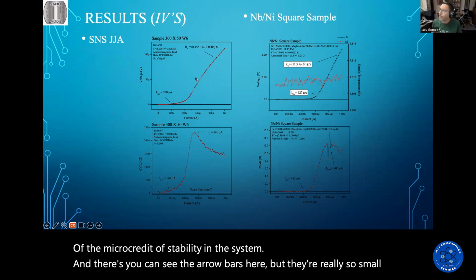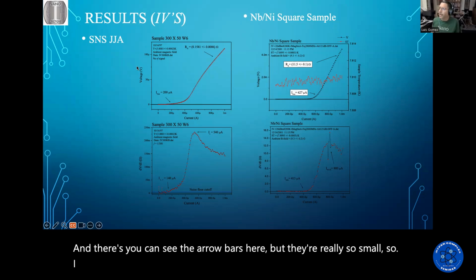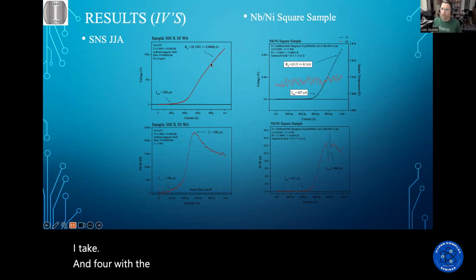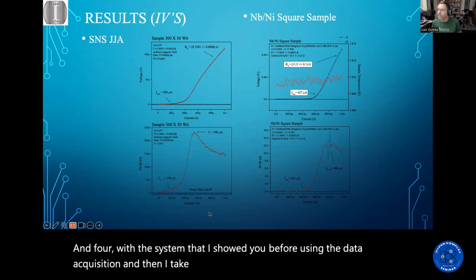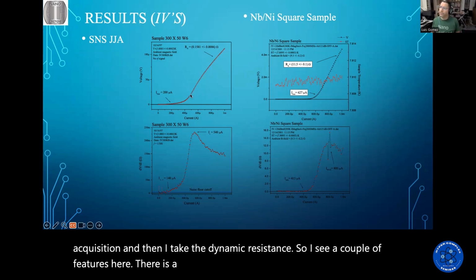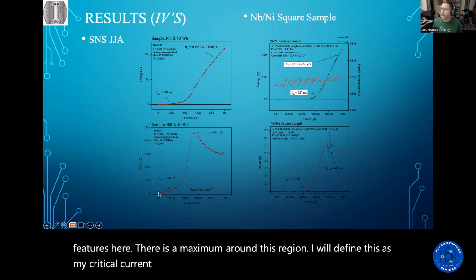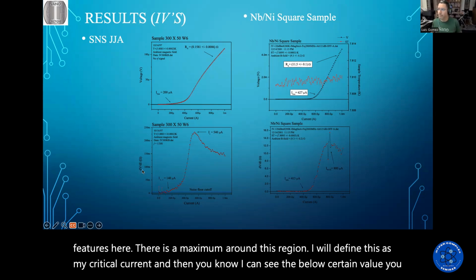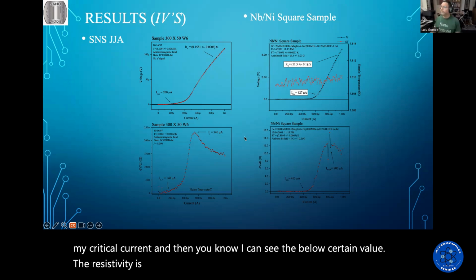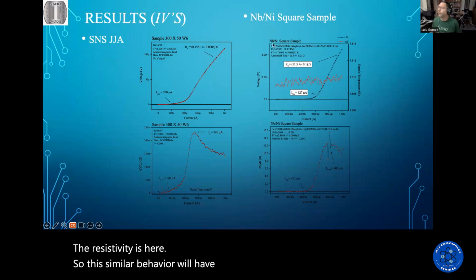So I take an IV with the system I showed you before using the data acquisition, and then I take the dynamic resistance. I see a couple of features here: there is a maximum around this region, which I will define as my critical current, and then below a certain value the resistivity is 0.